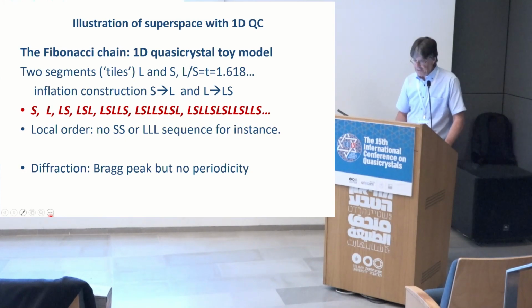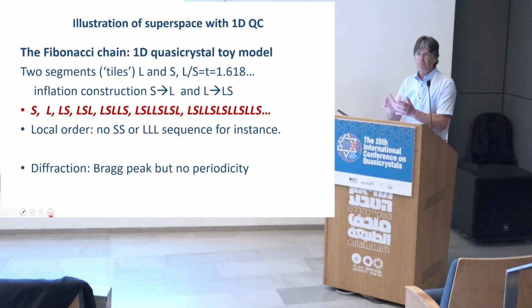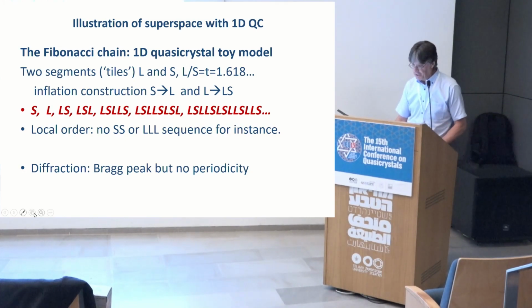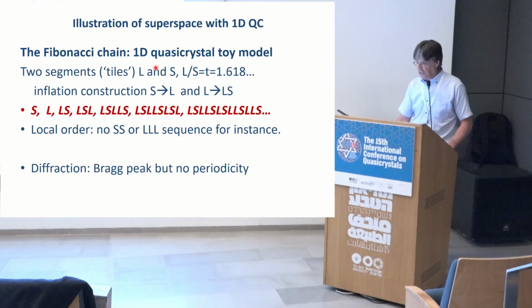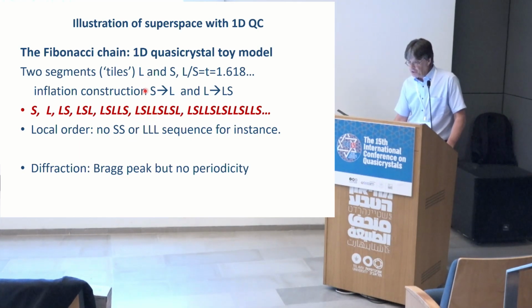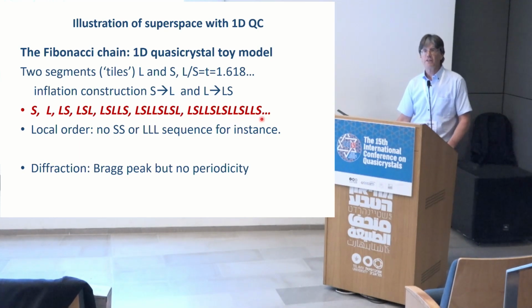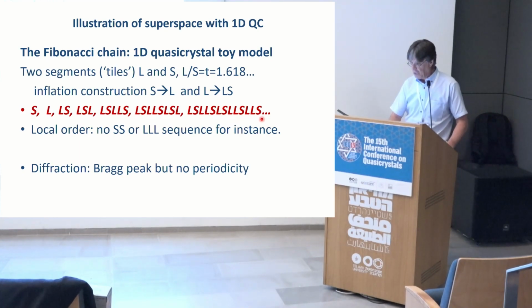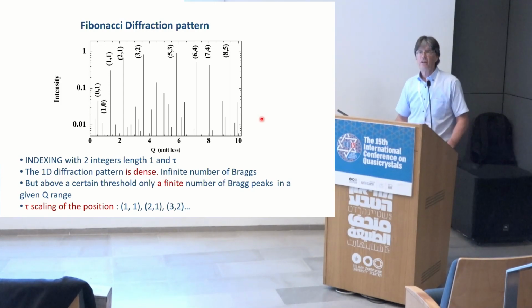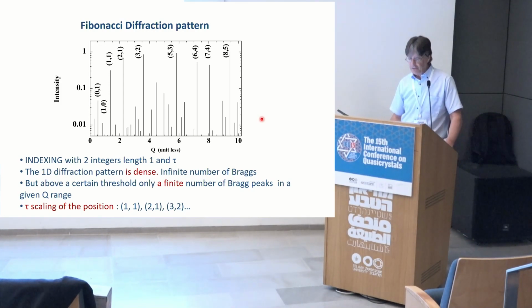So to illustrate that, I will go rapidly. I don't want to go into too much detail on this. I will be using this Fibonacci chain, which can be constructed by the so-called inflation construction. You have two tiles, long and short. You substitute the short by the long, and the long by the long-short, and in the end you have this infinite sequence, which is non-periodic. And if you look at the diffraction pattern of this Fibonacci chain, it's a kind of prototype of quasicrystals.